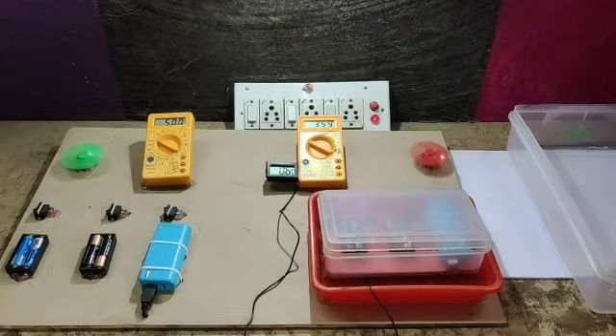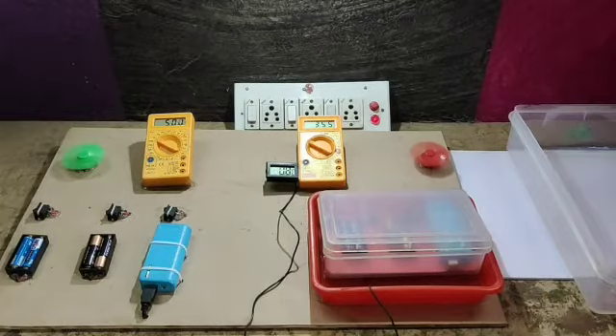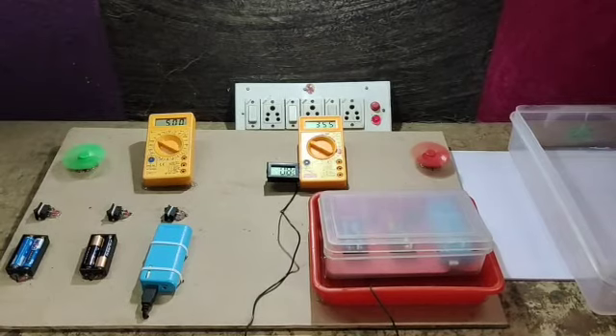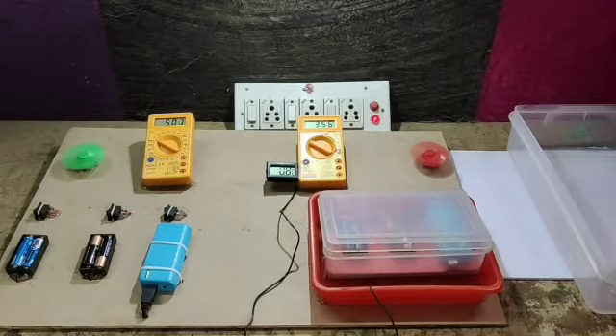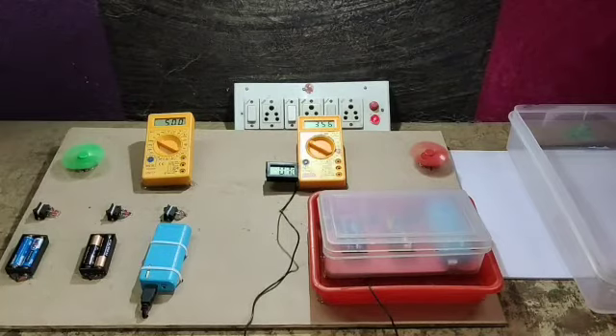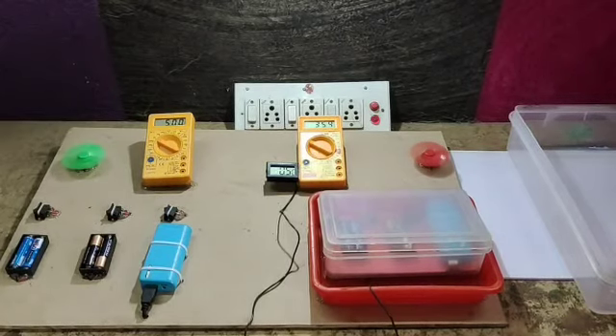And as the temperature reduces, the capability of the battery reduces by 20 to 30%, and we will get only 70% of the power. And as the temperature increases, there is a chance of the battery getting spoiled or the battery may explode at high temperature. So with this we can decide that lithium polymer batteries work better at 20 to 40 degrees centigrade. So if you are using any lithium battery, use it between 20 and 40 degrees so that you will get maximum output.